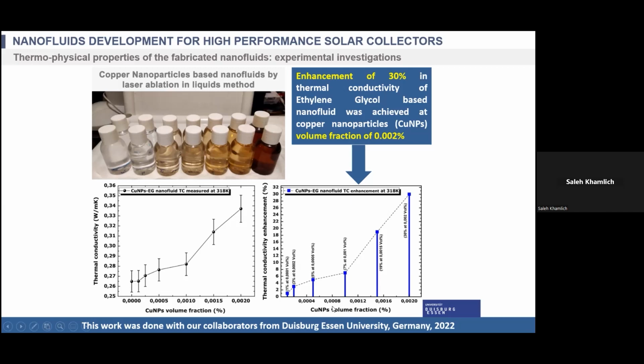So by changing the volume fractions, it shows clearly that at 0.002, as I showed you, is 30%. 0.0016 is around 19%. Even going down to 0.0004, it's around 5% enhancement, which is fine in this range. But by showing this, we show clearly that using highly stable nanoparticles, made with techniques which allow you to have very narrow nanoparticles and electrostatically stable, could really lead to what we call higher efficiencies at the end of the day.